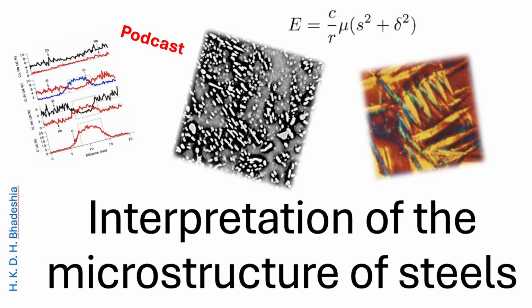That makes perfect sense. But if martensite is diffusionless, why does tempering require heat and time? Isn't that just reintroducing diffusion? That's a great question. Tempering happens after the transformation is complete. The heat you apply, even at low temperatures, say 190 degrees C, provides the mobility needed to relieve the strain.